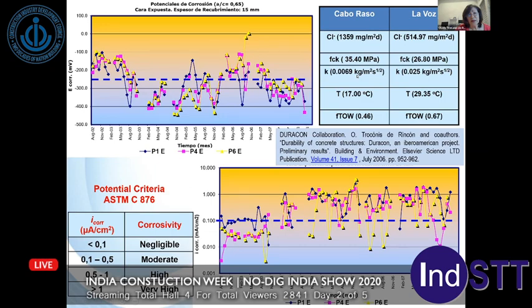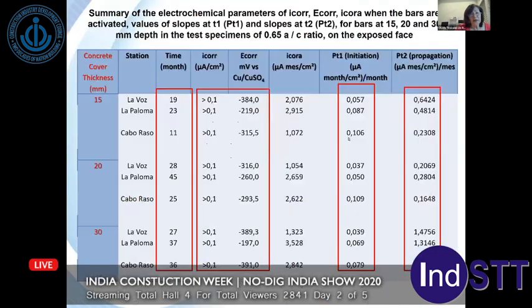The table is a summary of the findings in the test stations, where the values of the slope are also a very important fact to consider for modeling. We found in all the cases the slope in the initiation period less than 0.1, and in the propagation period, of course, higher than 0.1 in all the test stations. This is another parameter that maybe we need to analyze in the modeling.